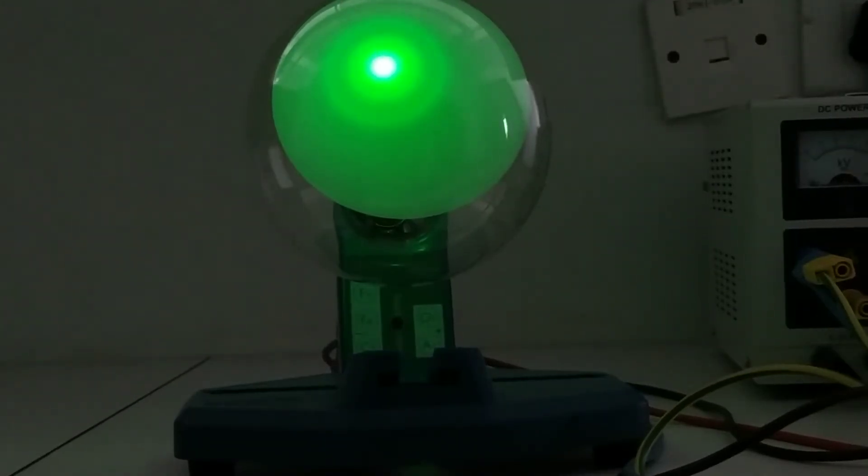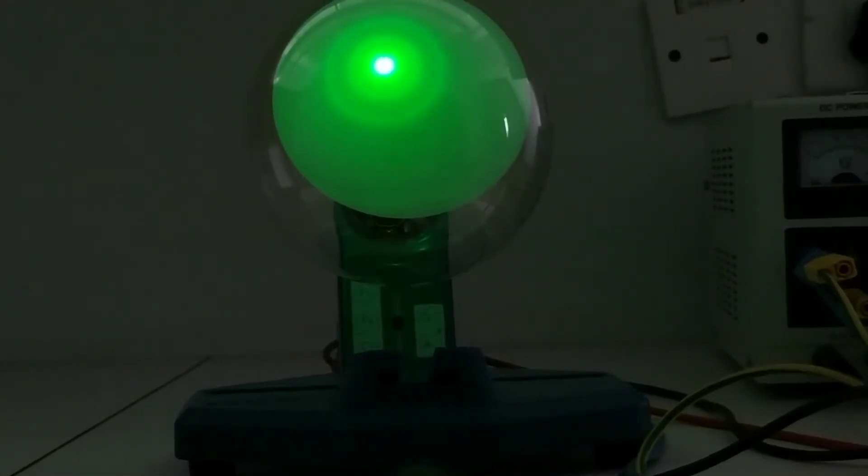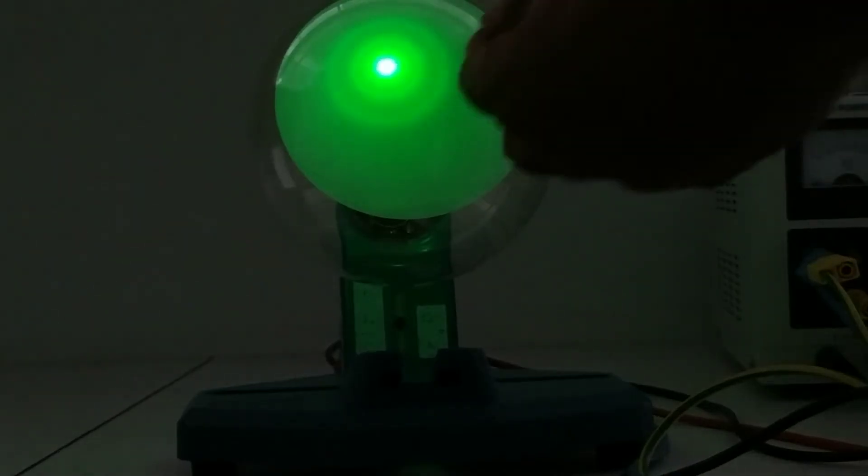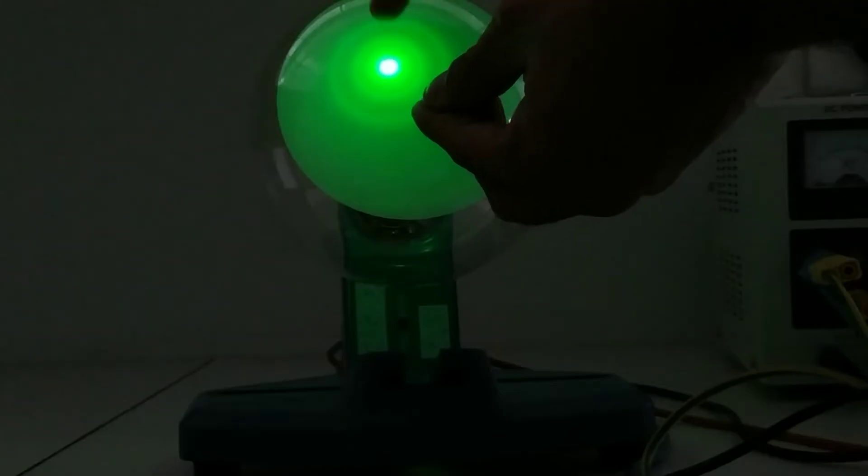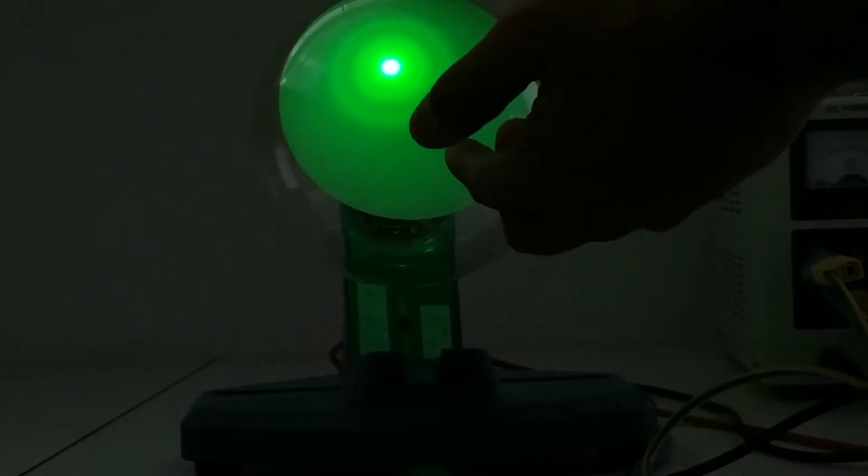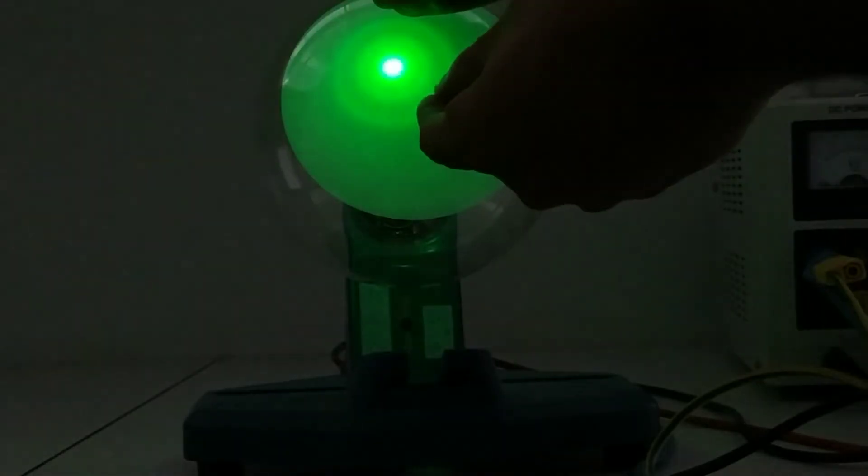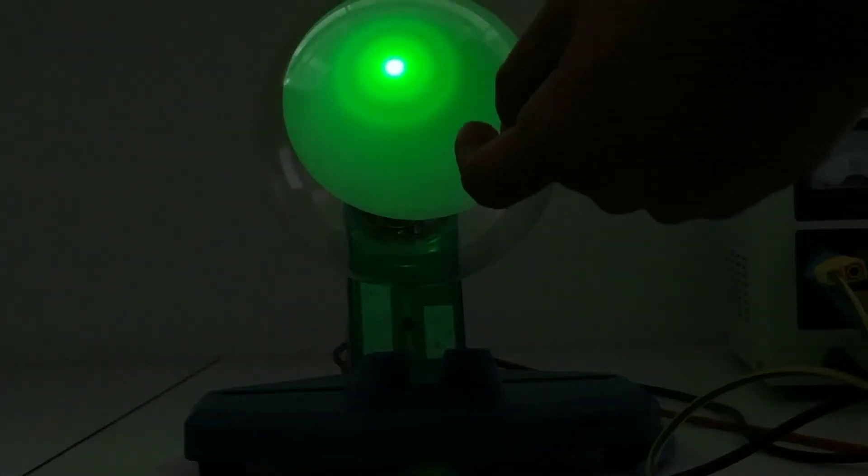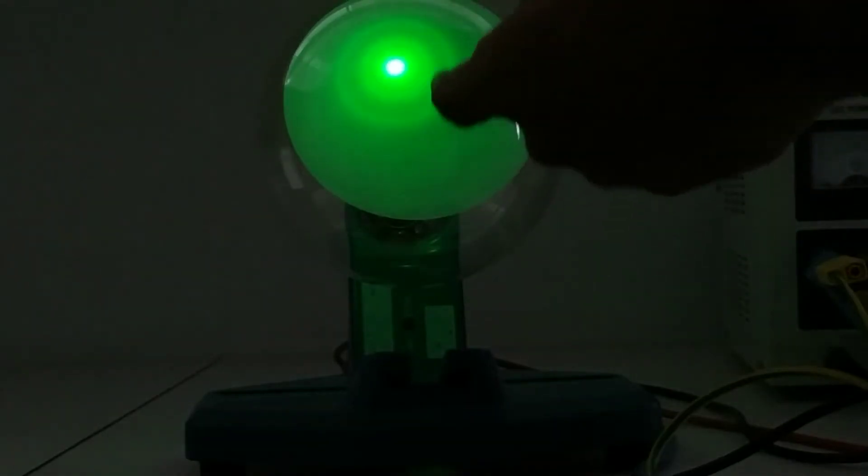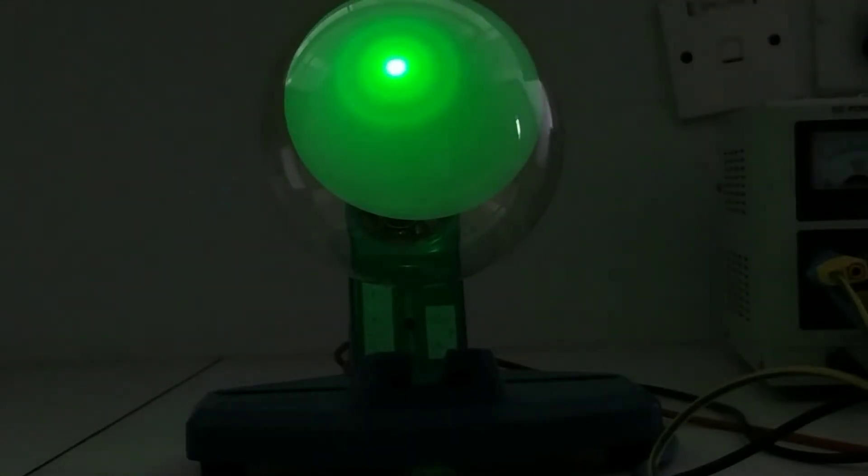There are actually two rings in the system. What you do next is you take a piece of graph paper or a measuring tape and you put them across your rings and calculate the diameter of the ring on the surface of this sphere, this bulb. One has to be very careful while doing it - just put the paper or measuring tape over here and measure the diameters. You can take one or two values and take the mean. Same thing you do with the inner ring. One ring corresponds to one of the lattice planes of graphite, the other ring corresponds to another lattice plane of the graphite, d1 and d2.